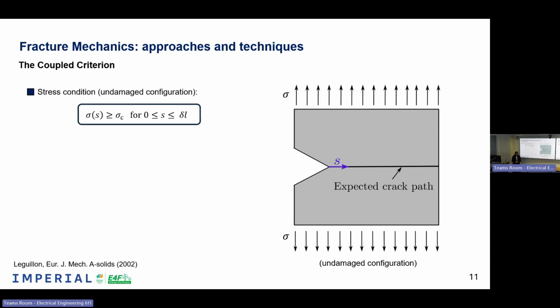One of these is the coupled criterion. It is a criterion developed by Leguillon in 2002, and it is able to predict both crack nucleation and crack propagation. It is based on two different conditions. So first of all, we assume an expected crack path in the solid. So we select a certain crack path, and over this crack path, we measure the stress condition, where we compare the tensile stress with respect to a critical value that is the tensile strength.